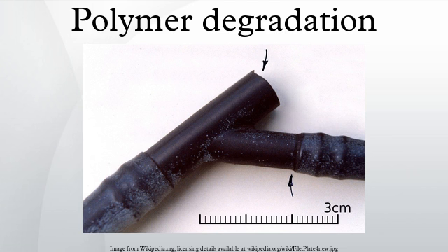Chlorine-induced cracking. Another highly reactive gas is chlorine, which will attack susceptible polymers such as acetal resin and polybutylene pipework. There have been many examples of such pipes and acetal fittings failing in properties in the US as a result of chlorine-induced cracking. In essence, the gas attacks sensitive parts of the chain molecules, oxidizing the chains and ultimately causing chain cleavage. The root cause is traces of chlorine in the water supply, added for its antibacterial action, attack occurring even at parts per million traces of the dissolved gas.